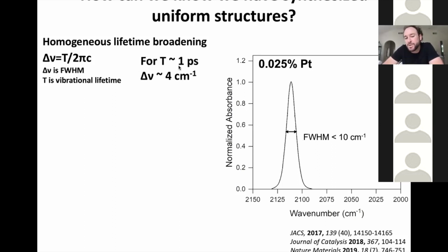So the line width should be related to the lifetime that this vibrationally excited state lives. And for CO on most metals, a good guess is about 1 picosecond. And so here you come up with a bandwidth for a homogeneous broadening of about 4 inverse centimeters or so. So we're a little bit higher than that in the samples that we make, but not a ton. This is a really nice paper for an overview of these sorts of broadening things.